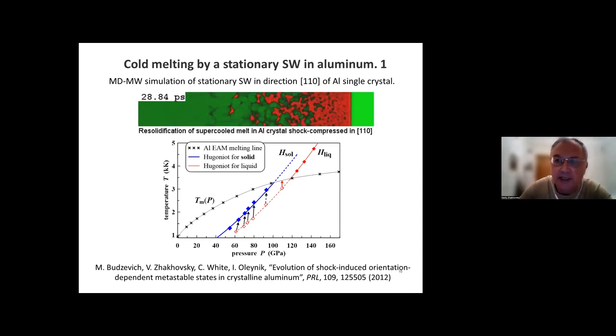kinetic coefficients like self-diffusion. So, in order to analyze this mechanism of cold melting, in a paper almost 10 years old, we performed molecular dynamics simulation in a moving window and applied a shockwave to an aluminum single crystal. So as you see, usually in this format, a supercooled melt is formed by the shock front, and then it recovers to the solid again.